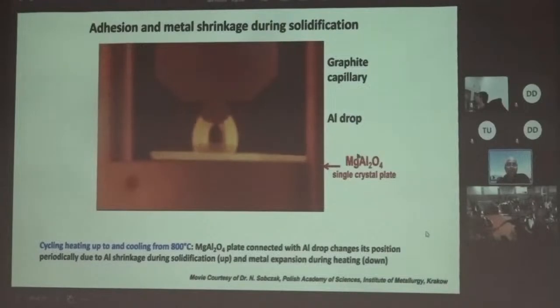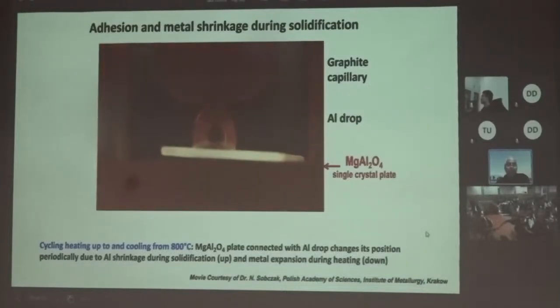Here you can see an aluminum drop in contact with this magnesium spinel. When you heat it, you can see the bonding here. When you cool, the plate is actually lifted up because the bonding is very good.